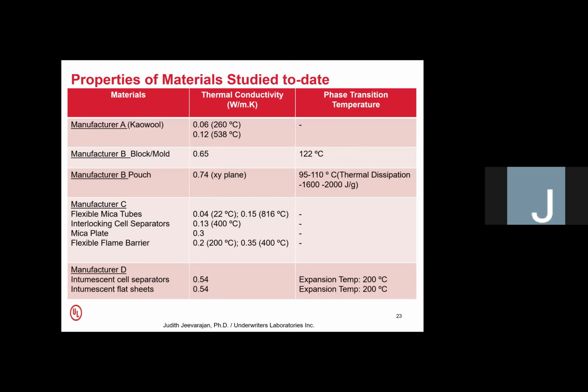So one of the things we did was look at the material properties of these different materials that we studied, mainly manufacturers A, B, C, and D. And what was observed was that whenever the thermal conductivity was a little high, as you see with manufacturer B, it does prevent propagation. The intumescent cell separators also had a little higher thermal conductivity, but from our results, we did not find that to be as effective as B and C. And if you recall the designs, B was really a block mold type of design, whereas manufacturer D had intercell separators that were just plates that we placed in between the cells.